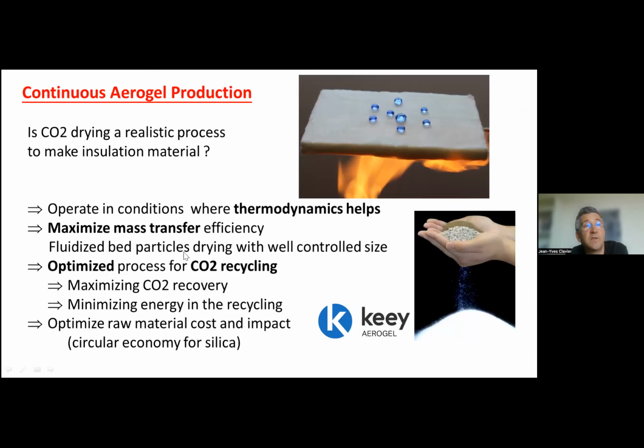The last one I want to introduce is aerogel formation. I know Pavel will speak of it, so I will leave him detailing more, but we are also working a lot on aerogel formation, drying of a gel with CO2 to make insulation material, very high quality insulation material. It exists in form of blankets like this, but what we do at Keey is making basically powders and beads of fine particles of aerogel that can be then introduced in some insulation material to be used in construction or in the insulation barrier to be introduced in the batteries of cars. These are two very growing markets, and the demands are huge for these powder aerogel to be introduced in